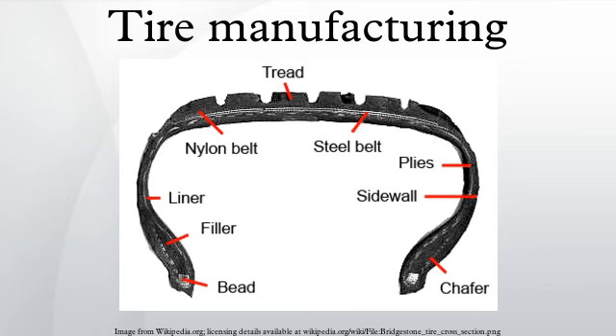Sidewall: Sidewalls are non-reinforced extruded profiles with additives to give the sides of the tire good abrasion resistance and environmental resistance. Additives used in sidewall compounds include antioxidants and anti-ozonants. Sidewall extrusions are non-symmetrical and provide a thick rubber area to enable molding of raised letters. The sidewalls give the tire resistance against the environment and play an important role in the strengthening of the tire.